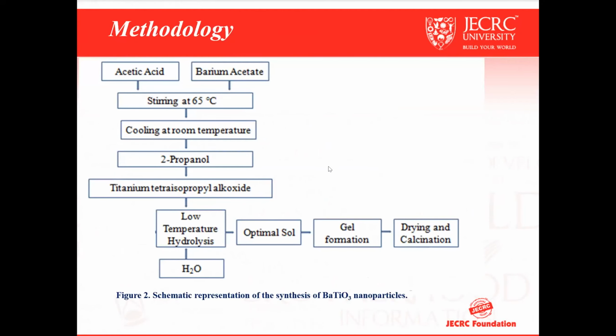This slide contains the methodology for the formation of barium titanate nanoparticles by the sol-gel route, and the whole process has three steps. In the first step, we took the precursor barium acetate and heated it at 65 degrees centigrade with stirring, then cooled it to room temperature. Then we added the other precursors, propanol and TTIP, and cooled the mixture at low temperature. Then we got the optimum sol. After keeping it, we get the gel, and after drying and calcination, we get barium titanate.